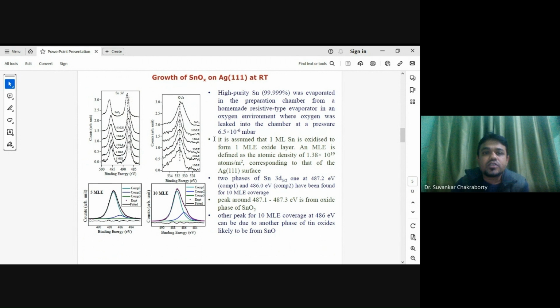So we have grown that SnO by evaporating Sn in an oxygen atmosphere, and we assume that one monolayer of Sn gives SnO, and we do the XPS after growing each monolayer. We can see that with an increase in thickness, the Sn 3d peak shifts towards the higher binding energy, but oxygen stays the same. The only thing is there is some hump at the higher binding energy that we can see.